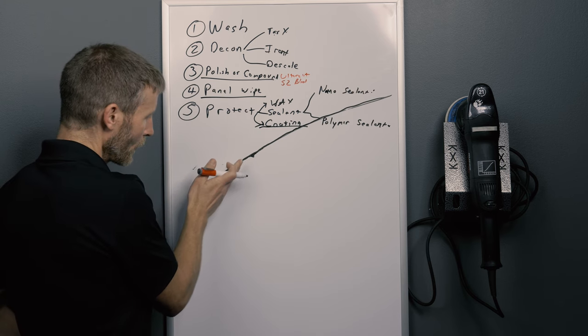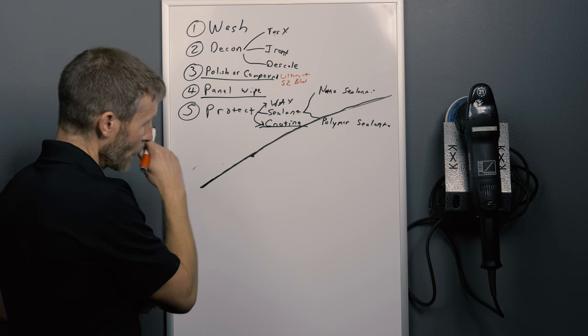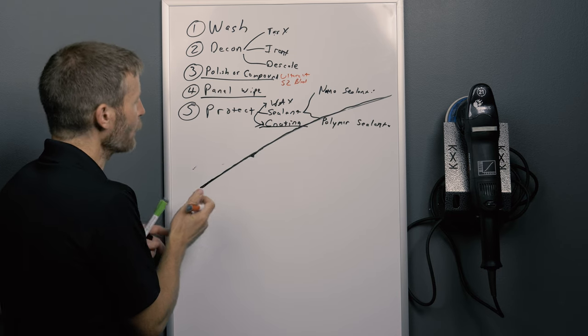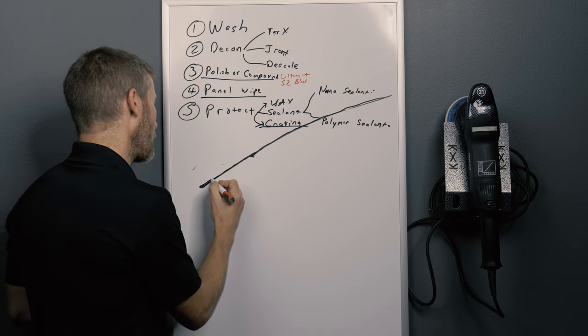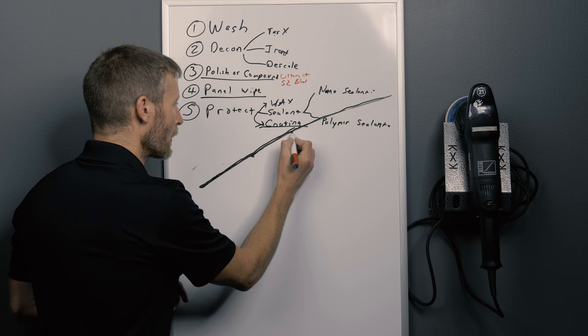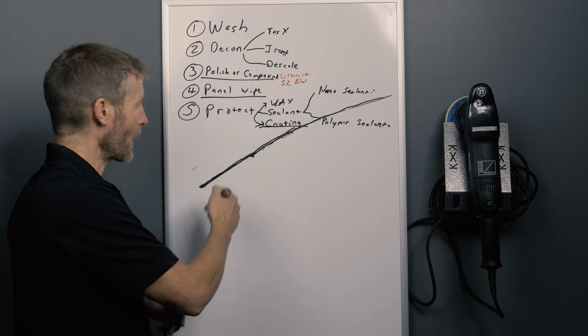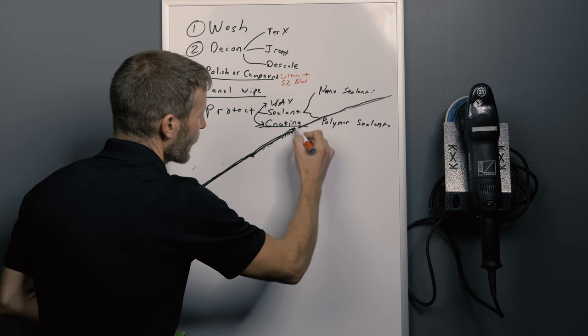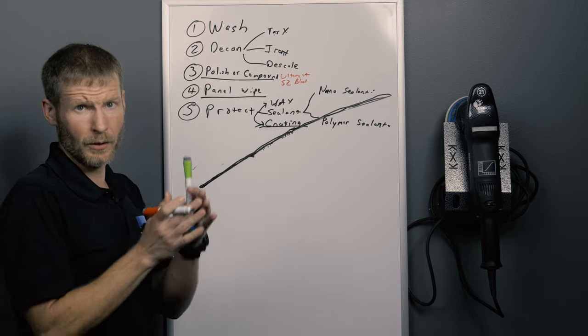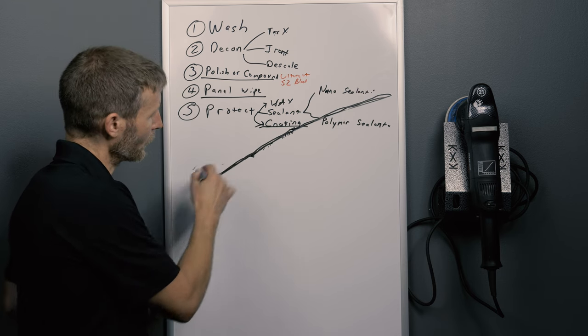So we've got our coating on there. When that coating first goes on the surface, it's a liquid. It's poured out of a bottle. You wipe it on. And then it's going to flash. You're going to wipe whatever is left over off. And the part that's supposed to stick to the paint is going to stick to the paint. Generally, we'll come back an hour later and put a second coat on. You don't have to. One coat would last good. But two coats is going to do better. But some of that coat is going to fill in the pores. It's going to soak down in here and fill in the pores and the paint. Create a base for that second coat. So now you've got this ceramic coating on here. It's undergoing something called a sol gel process. Basically, it's turning from a liquid to a gel and then to a solid.